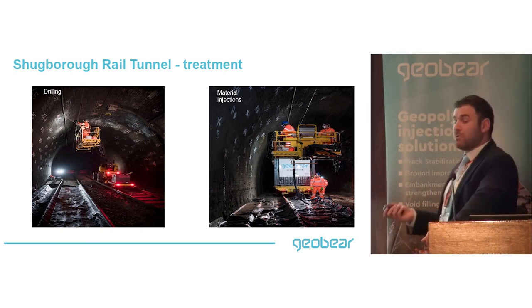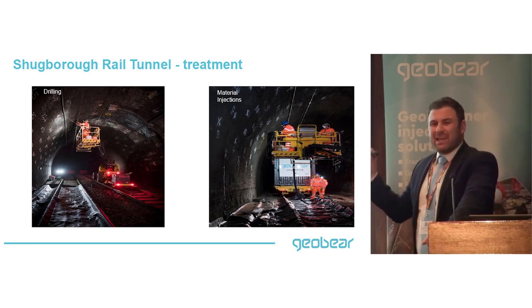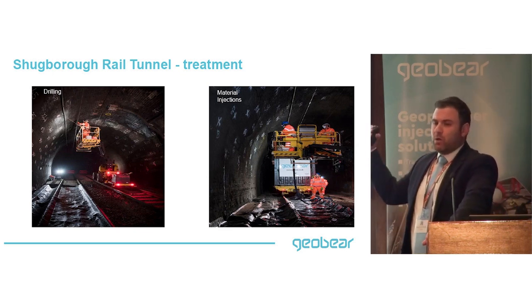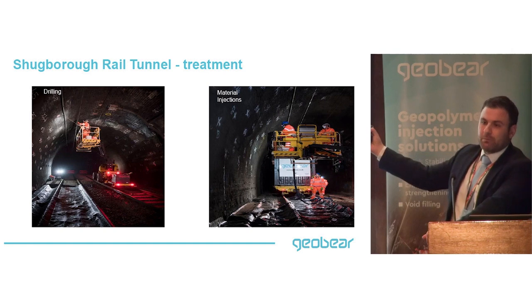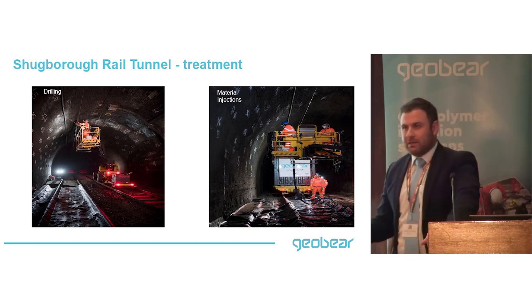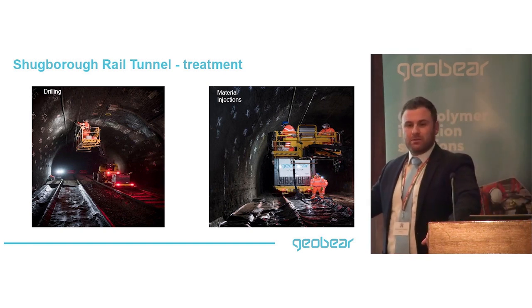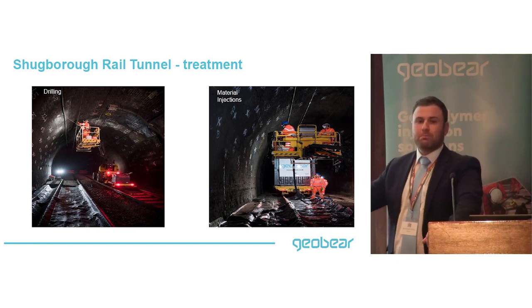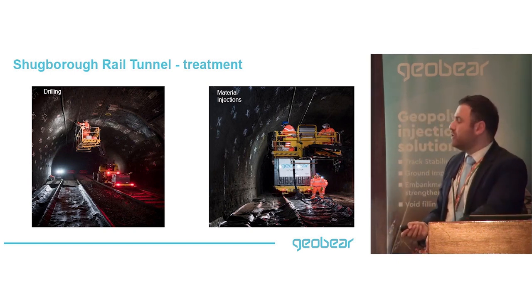The advantage of this approach is that you're not really adding any extra dead loading. If you wanted to use grouting in this scenario, grout has probably 10 or 20 times the weight of the polymer we use, so you'd be imposing extra dead loading on the tunnel lining.